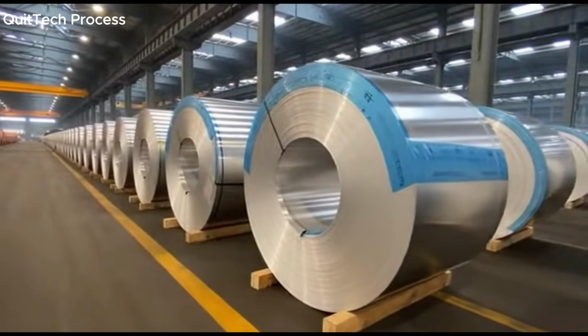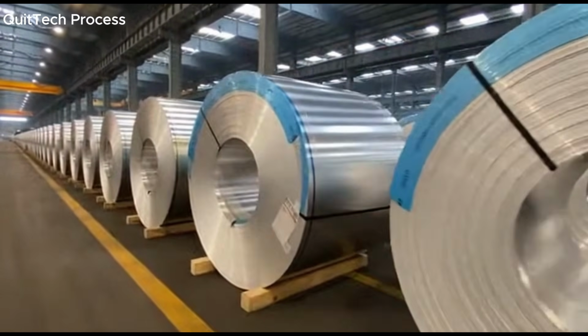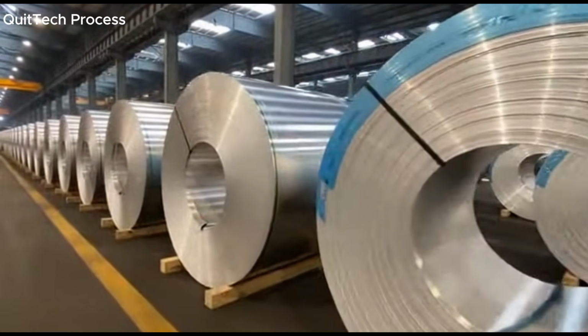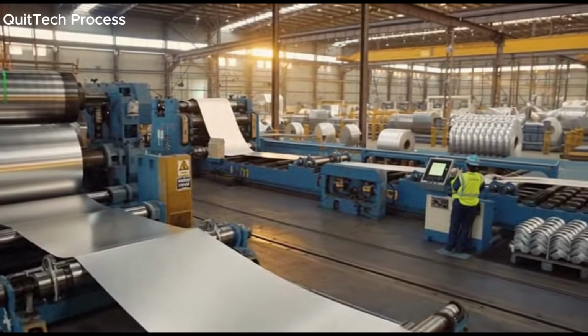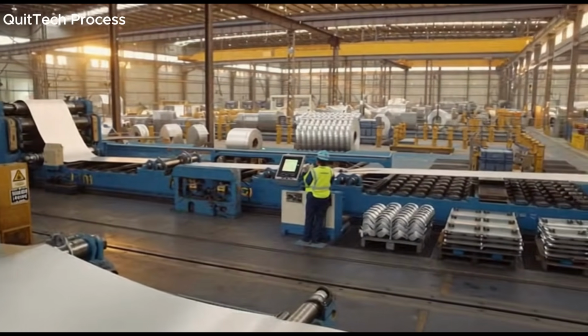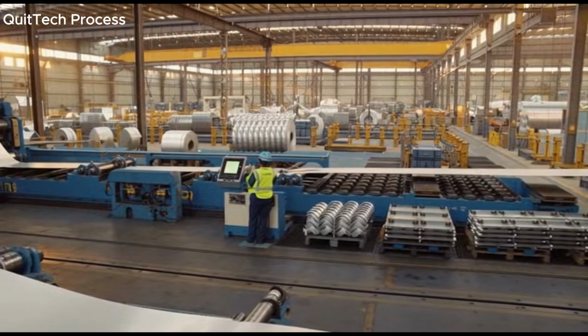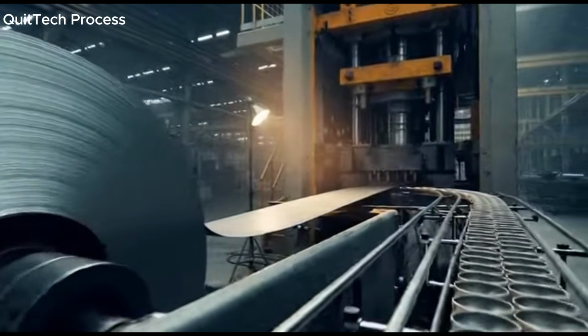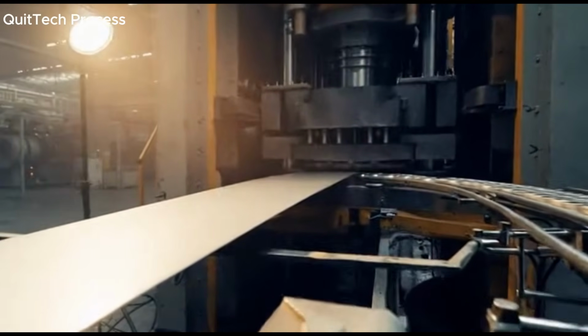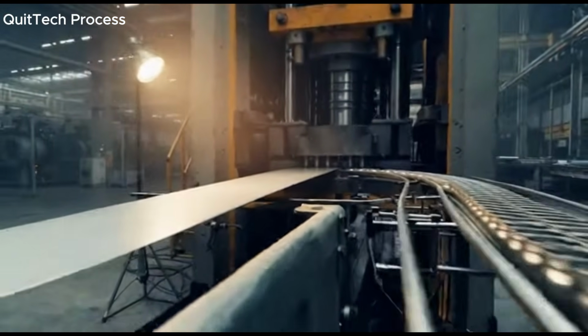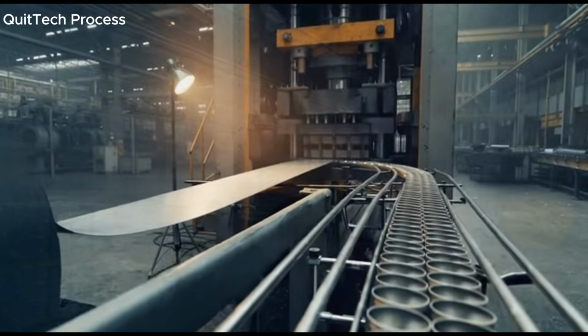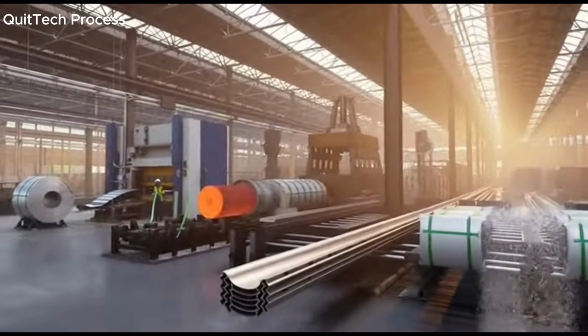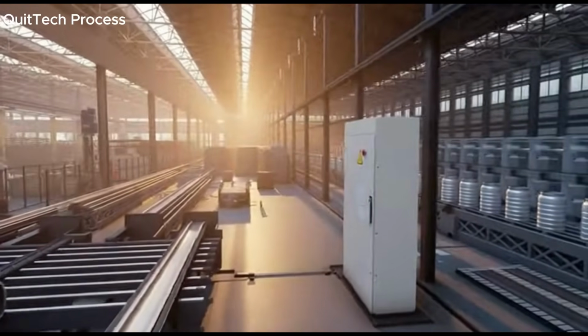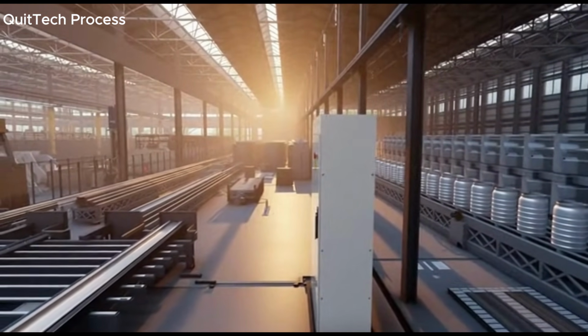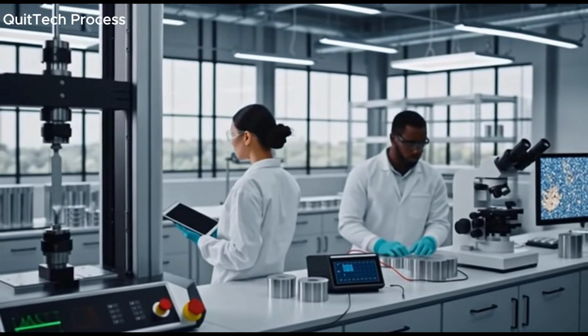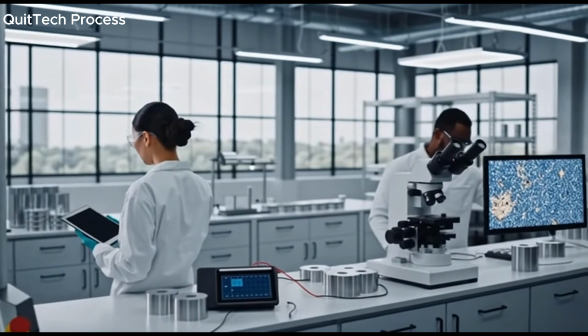In more advanced facilities, inert gases, typically argon or in some applications chlorine, are injected at carefully controlled pressure through submerged lances. Tiny bubbles travel upward through the molten aluminum, capturing dissolved hydrogen and excess oxygen, carrying them to the surface for removal. The result is metal with dramatically reduced gas content, a critical quality parameter for the most demanding applications. Temperature is maintained precisely throughout this entire stage. The aluminum must remain liquid and workable while refining proceeds, but must not overheat to the point where new contamination is introduced.